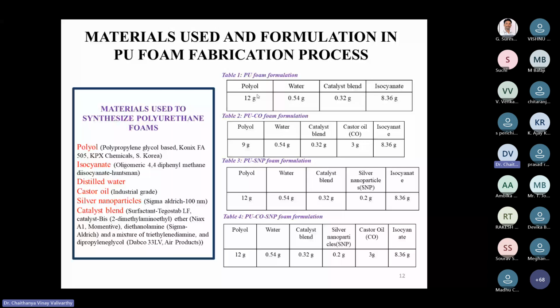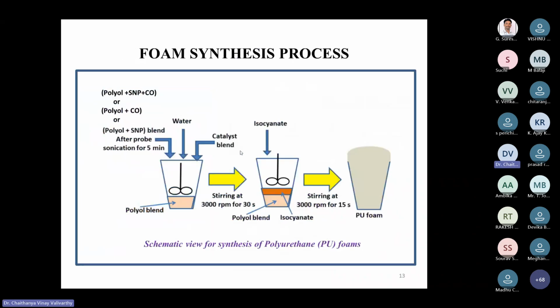So for these foams, two major components are there: one is polyol and the other is diisocyanate. Here the polyol and isocyanate play an important role in forming a PU foam, and we also have water and catalyst. And if I want to make any PU foam with castor oil, we can reduce the polyol content and increase the castor oil content. So by using the synthesis mechanism, we are preparing these PU foams, and also with PU SNP. For the first time, we have combined castor oil based and SNP together to make a PU foam, and we use this PU foam to convert it into the auxetic foams. Further, we can discuss how we can convert it. So this is the foam synthesis process.